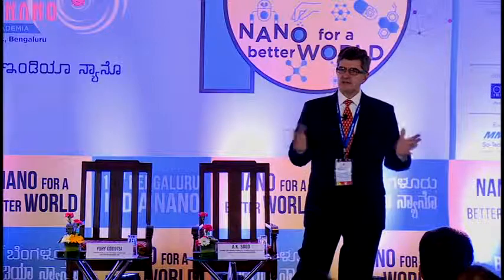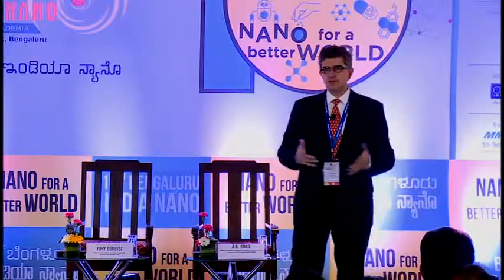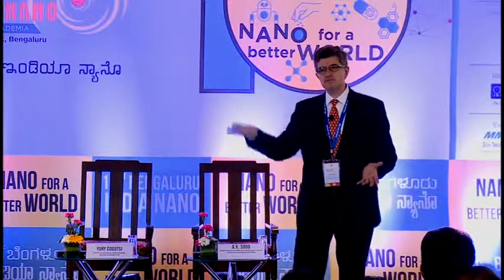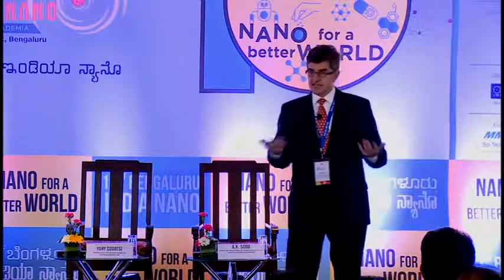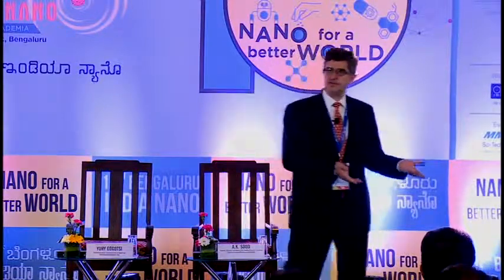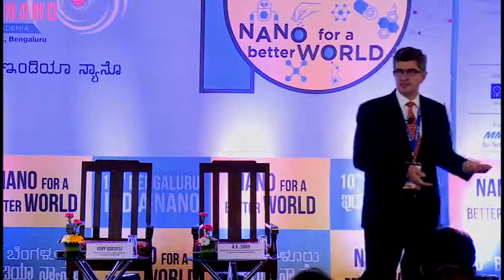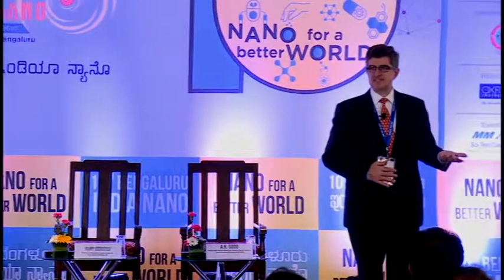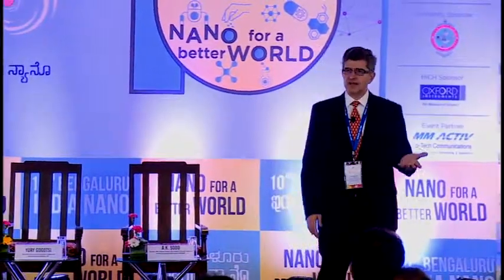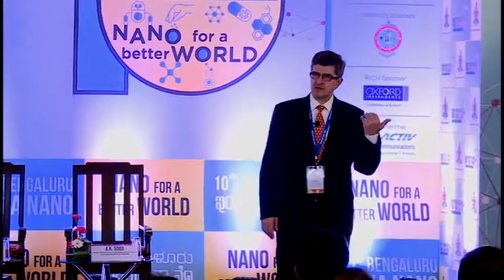So far, we can make single flakes up to about 20 microns because we produce them by wet chemical method, in etching. It's still very large if you look at the size of the flakes for other materials. For example, for molybdenum disulfide produced by wet chemical synthesis, you will hardly find more than 1 micron sized flake. High strength of MAX phases allowed this.